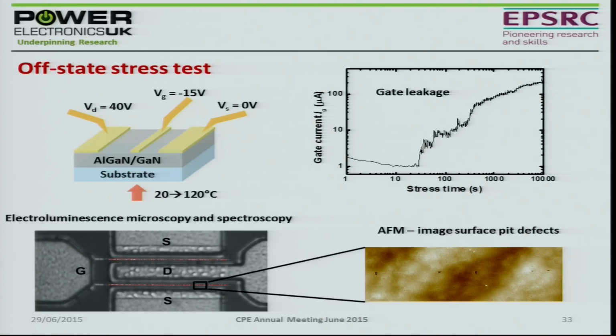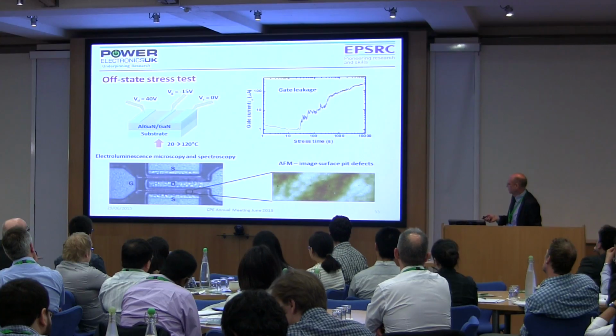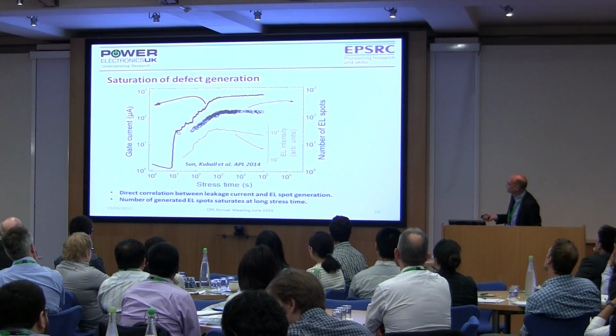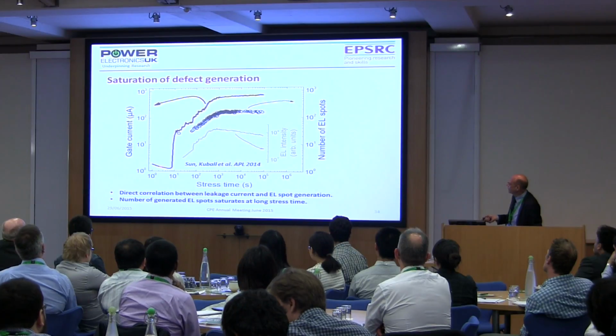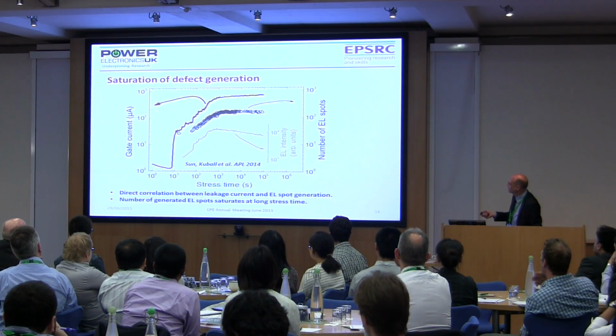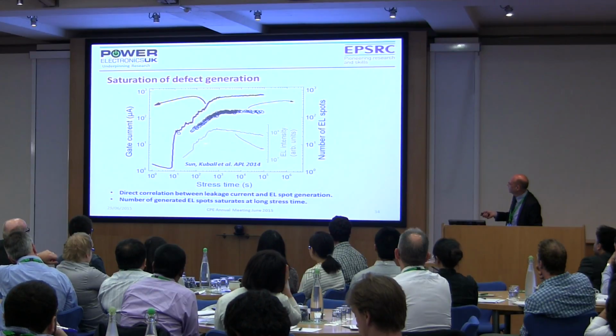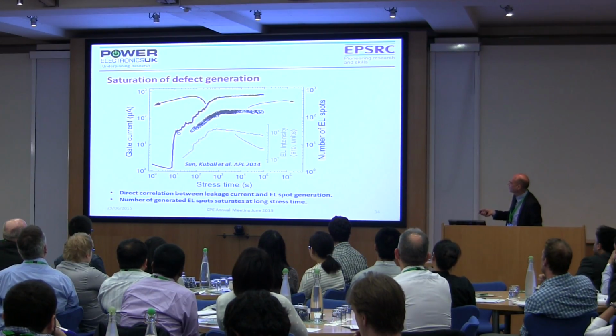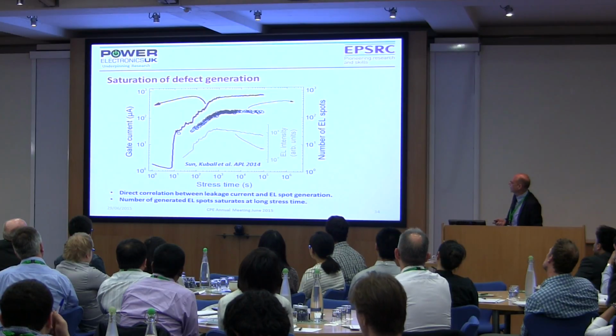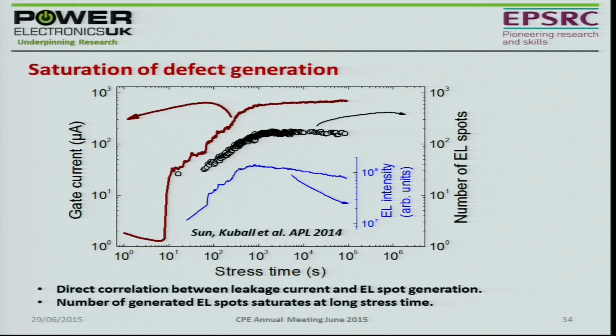And they emit light, so they're quite easy to see. They emit blue light. And this shows that curve, the gate leakage again, increasing with time. And here's the electroluminescence, the light that comes out of that gate structure. And you can see it pretty much mirrors that. So you can just look at the light that comes out around the gate finger, and it gives you a good indication of how well you've made the structure. If there's no light, then you've made an effective structure.